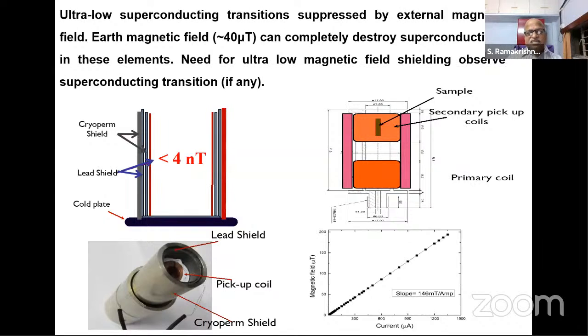Luckily, there are systems like Cryoperm. It's a high mu metal shield at lower temperatures. So you make two of them, then use lead. Lead is a good superconductor. It expels the magnetic field, so that also will act as a shield. So we made a shield out of this and made sure that the field inside is less than 4 nanotesla.